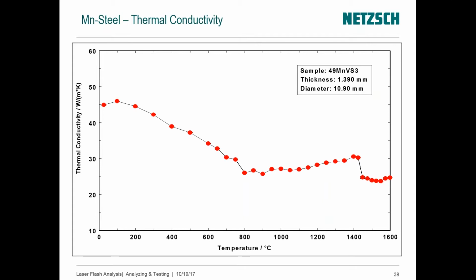As you see here, one can still see the phase change around 700 degrees if conductivity was measured directly. It might not be so obvious to see really a phase change around 700 some degrees. By the time it is combined, obviously, whenever the sample melts, it's clearly seen above 1400 degrees Celsius. But again, this is a statement for why people tend to use the laser flash apparatus, the laser flash techniques